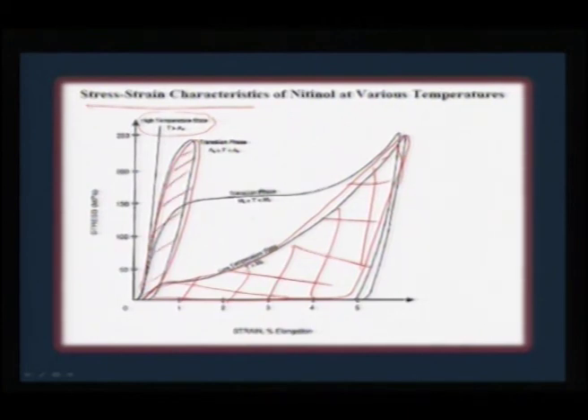So, this is the way the stress strain curve applies for nitinol in the high temperature and low temperature regimes. Plus, the transition from the martensite to austenite phase is clearly seen in this regime, and this is also reversible, which is highly selective. So, you can clearly make out the difference between the austenite to martensite transformation, which gives you the allowance to play with the different applications depending on whether it is needed in the high temperature phase or in the low temperature phase.